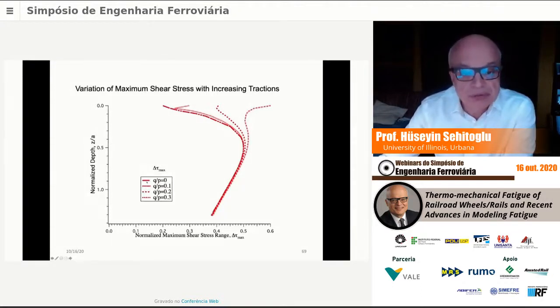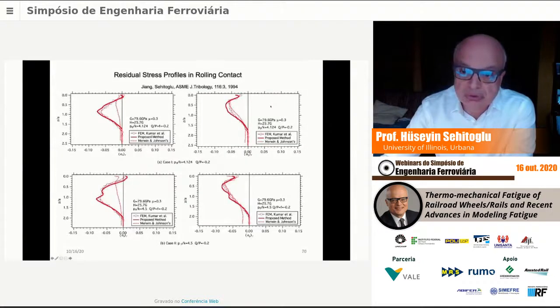So for Q over P equals zero, as you know, the maximum shear stress range is below the surface. That magnitude should be around here, 0.5, somewhere here below the surface. As we increase the shear tractions, the maximum shear stress range moves to the surface. At Q over P equals 0.3, the maximum shear stress range is on the surface, and its magnitude is about 0.6. It's normalized with respect to the contact pressure, but it's going up. So one can get ratcheting, of course, in the pure rolling case, as well as in the case of finite shear tractions.